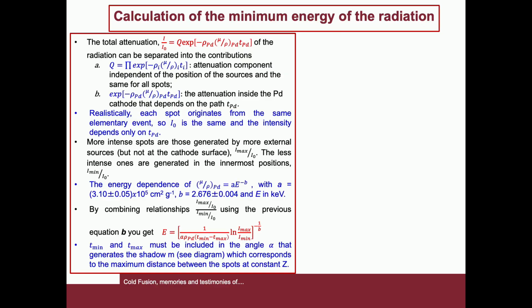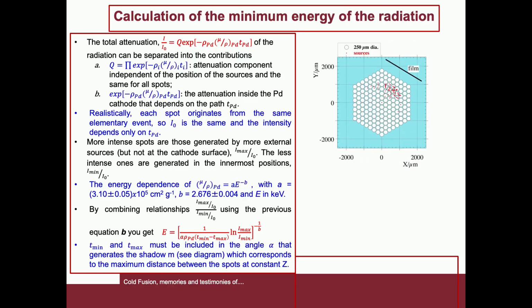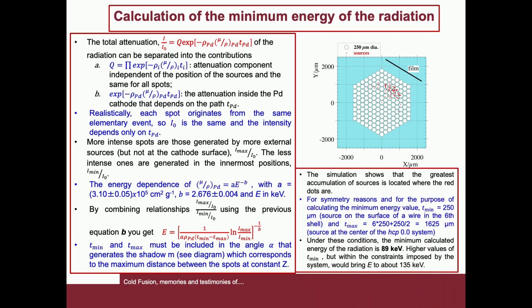It should be remembered that the palladium cathode consists of a certain number of wires. Realistically, each spot originates from the same elementary event. Therefore, I0 is the same and the intensity depends only on the path of the radiation in the palladium. More intense spots are those generated by more external sources, but not on the surface of the cathode, and therefore the ratio I max over I0 can be determined. The least intense spots are generated in the most internal position, and therefore the ratio I minimum over I0 can be determined. The dependency on energy of the palladium mass absorption coefficient is given by the exponential relationship written in blue.